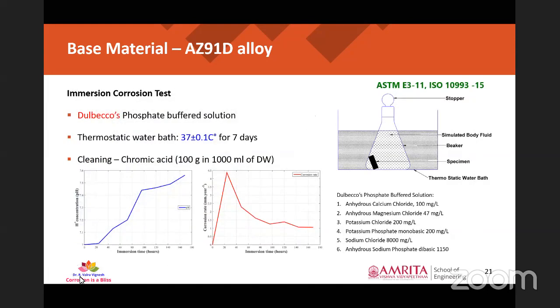Then for performing the immersion corrosion test, we followed ISO 10993-15 standards, where we have to simulate a normal human environment, and we maintained a temperature of 37 plus or minus 0.1 degrees Celsius. The corrosion test was done for a period of 7 days. After performing the corrosion test, the corroded specimens were cleaned using chromic acid, prepared by mixing 100 grams of chromium oxide in 1000 ml of distilled water. That was used to remove the corrosion products over the surface of the material.